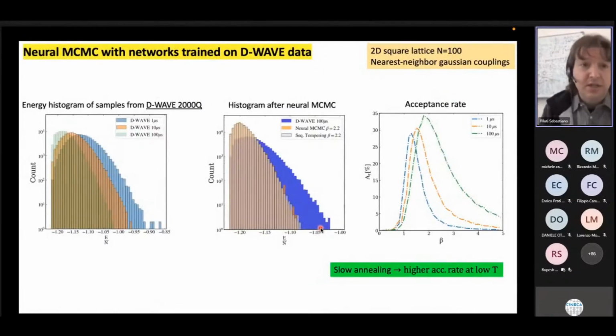Now, here is the interesting part, because here we work on data generated from the quantum annealer. And here on the left, you see some histograms of the energy distribution that you obtain from samples from the D-Wave quantum annealer. Here, the data are actually from the relatively old device, the 2000Q device. We are working on Advantage, and we obtained access to it via Cineca, via an ISCRA Class C project, and we're very grateful for that. And so you see the three data sets correspond to different annealing times.